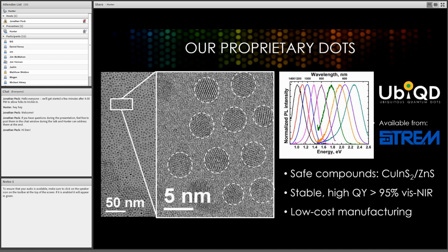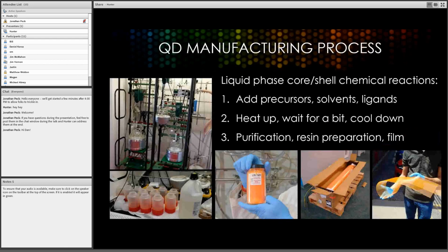Most of what we're doing with windows is with copper indium sulfide, but we can also make alloys, and that enables us to go deeper into the near IR. And if you do want to play around with these materials, they're available on Strem. We distribute to them for the research market. I'm not going to go into the details of our manufacturing process, but I'll show a few pictures of what it looks like. It's a liquid phase reaction for the core and the shell. We have a shell that protects the core from the outside world, and that's typically zinc sulfide.